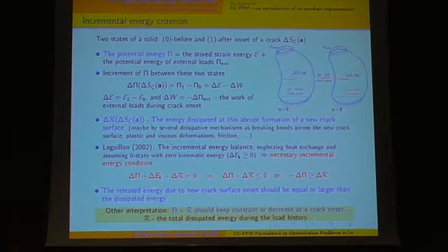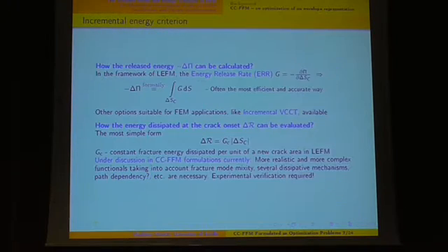And following Leguillon's hypothesis, the incremental energy balance leads to this necessary incremental condition. If we consider zero kinetic energy in the state zero, we arrive at this energetic condition, which can be written also in this way: that the released energy due to the new crack onset should be equal or larger than the dissipated energy in this onset. The other interpretation would be that the sum of the potential energy and the dissipated energy should stay constant or decrease at the crack onset, where R is the total dissipated energy during the load history.